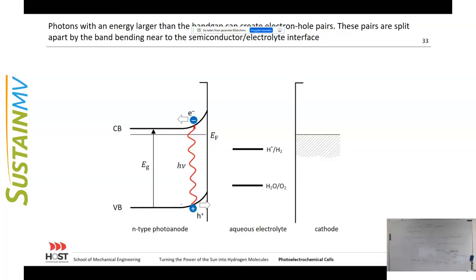Okay, now if we have a photon with an energy larger than the band gap, h times nu larger than Eg, then we can create, in the space charge area, which is the region where we have the band bending, an electron hole pair, creating an electron in the conduction band and leaving behind a positive hole in the valence band. And because of the band bending, the electron will be sucked to the left-hand side, and the hole will travel to the interface between the anode and the aqueous electrolyte.